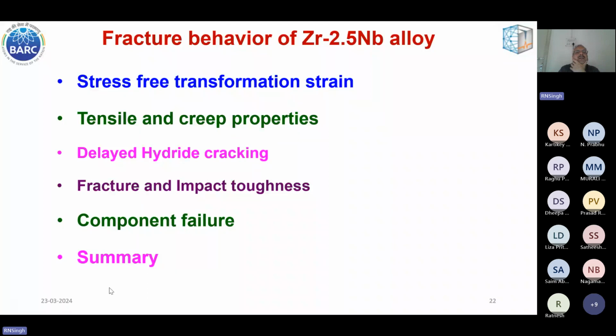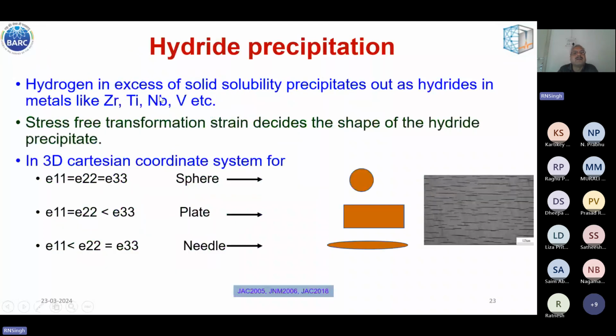Now, once hydrogen in excess of solid solubility precipitates out as hydrides in metals like zirconium, titanium, niobium, vanadium, etc., a stress-free transformation strain decides the shape of the hydride precipitate for solid state transformation. We all know from our basic physical metallurgy, in a 3D Cartesian coordinate system, if the 3 orthogonal transformation strains are equal, we end up with a spherical precipitate. If they are equal in 2 directions and less in the 3rd direction, we end up with a plate-shaped precipitate. If it is lower in 1 direction compared to the other 2 directions, then we end up with a needle-shaped precipitate. In the case of the zirconium hydrogen system, hydrides exhibit a plate-shaped precipitate.